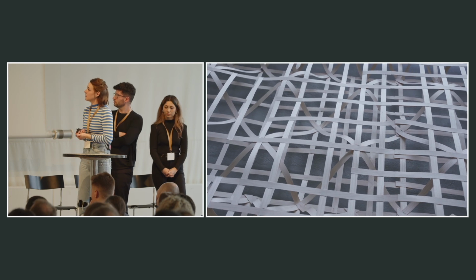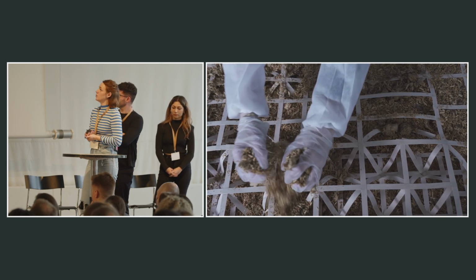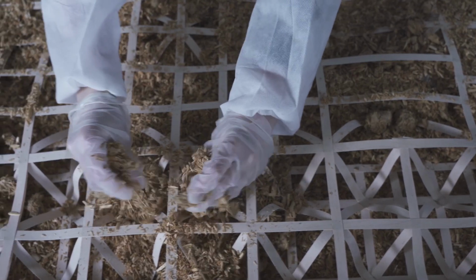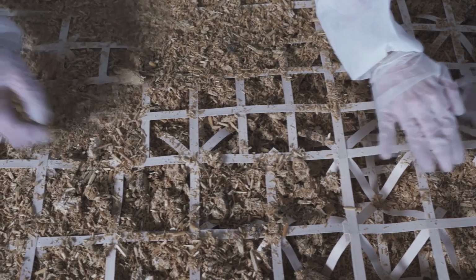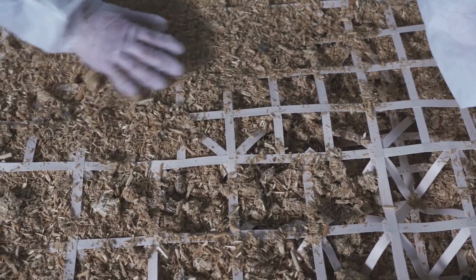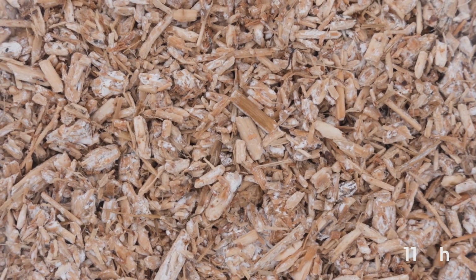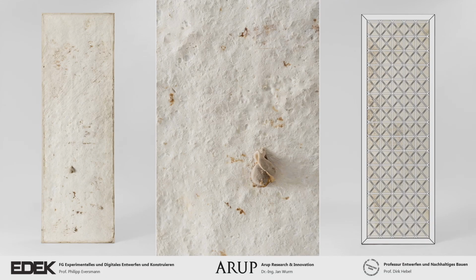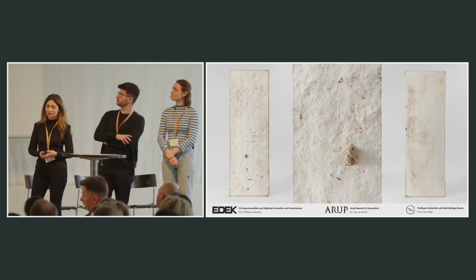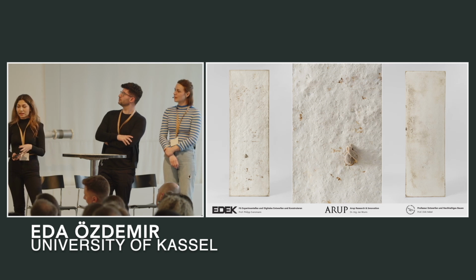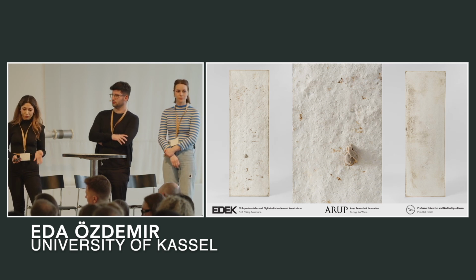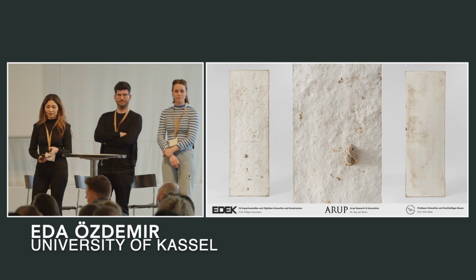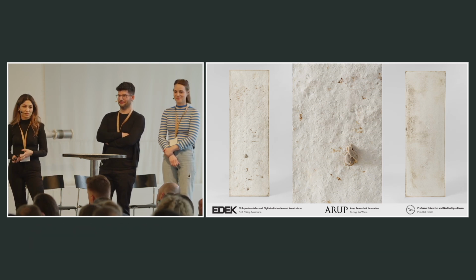Later on, we filled the lattices with a mycelium substrate. And within 1 to 2 weeks of cultivation in a controlled environment, the lattices were grown together with the mycelium substrate, creating the stable composite. Thanks to the veneer lattice fabrication method that we've developed, we made a full-scale partition wall that has a uniform lattice embedded in. This lattice is connected to an outer frame, as mentioned before, that increases stability and improves the bending and tension resistance of the composite.